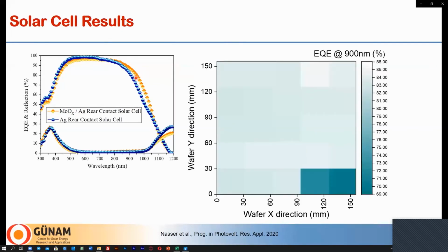We also checked the surface coverage of molybdenum oxide. So we did EQE mapping at 900 nanometers. We collected the EQE at a fixed wavelength of 900 nanometers, because this wavelength directly reflects the quality of the back side, since light at this wavelength or above can reach the back surface. You can see that the EQE has excellent surface coverage and excellent values, exceeding 78% at this wavelength over different positions of the wafer. Only in a small area here at the corner does the EQE show between 70 and 72%. This is normal and may arise from slight inhomogeneity in molybdenum oxide thickness across the wafer. Still, this homogeneous EQE response in the infrared confirms adequate conformal surface coverage on the textured back surface of the wafer.